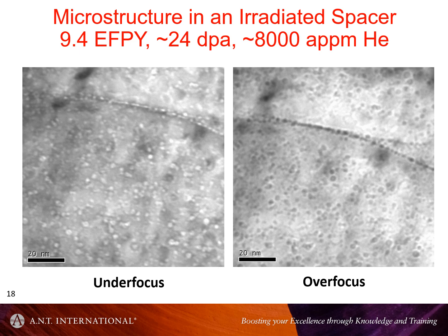So I had some young people just starting, who didn't have any experience with the TEM, and they were quite mocking, basically, when I came over, and they said, you don't have the bubbles on the grain boundaries. So I said, let me sit down. So I spent half an hour aligning the microscope, and then produced these two images here. And basically, you've just got to align the microscope. The difficulty, and why people weren't seeing it in the past often, I think, is because you didn't have the microscope aligned. So one of those young chaps, or a couple of them actually, went away and published this later without giving any acknowledgement to the fact that I was the one who aligned the microscope for them and took the pictures. Anyway,